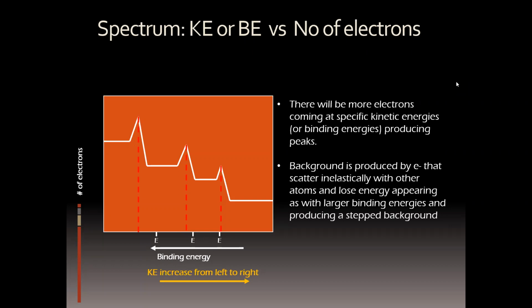And this stepping here has to do with the fact that you're not only getting electrons from those core electrons, you're getting all sorts of electrons. And electrons that come out with very small kinetic energy, it is because they lose a lot of energy on the way out, but they just introduce a lot of noise and they give you this stepped background. You can plot it. The usual way to plot this is not with respect to the kinetic energy that they have when they come out, but you can transform this using tables to extract the binding energy. If you have little kinetic energy left, that means that you used a lot of energy for the binding. So you had a lot of binding energy. So it goes from little on the right to a lot on the left. So it is plotted in the opposite direction.